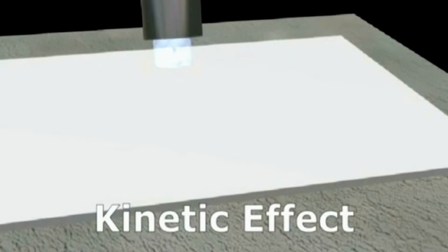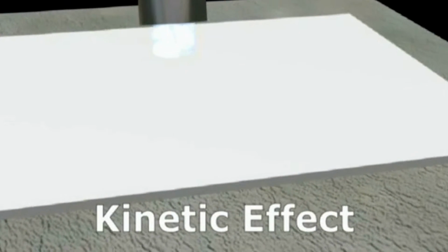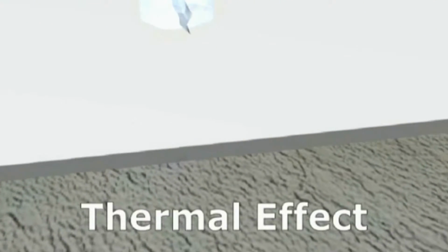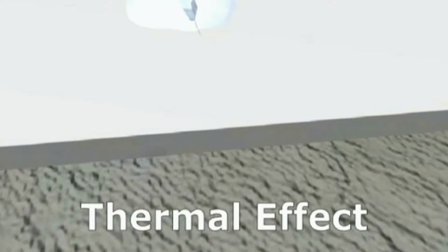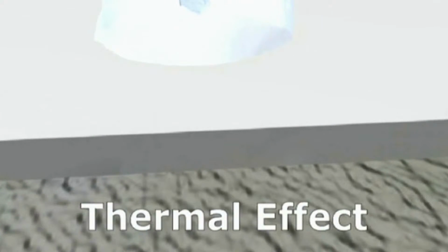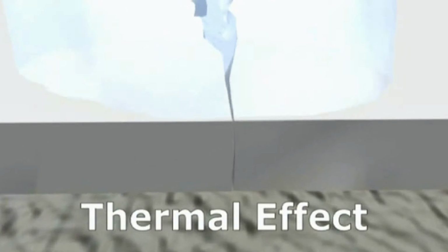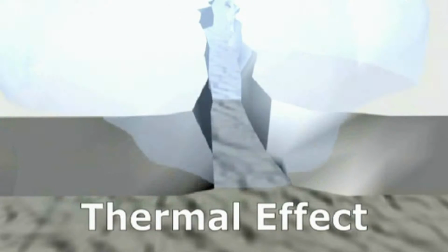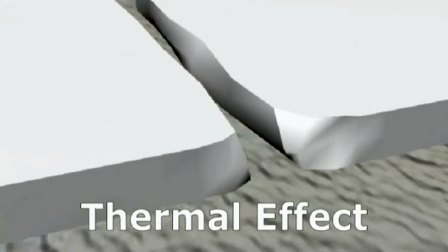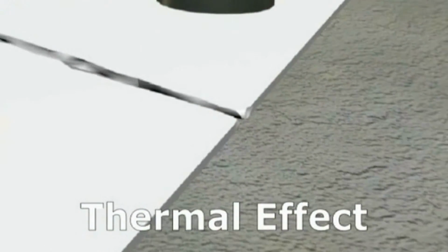When dry ice pellets strike a surface at the speed of sound, any coating on the surface is cracked and loosened. The low temperature of dry ice pellets makes the coating brittle, cracking and loosening it as a result of the reduced bonding between the coating and the underlying surface. This allows dry ice to permeate the coating.